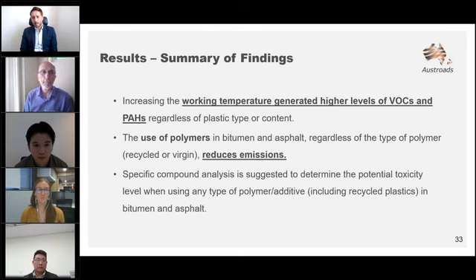No. Well, it's probably not related to slide 33, which is about emissions, but no, in general, we found it difficult to mix more than 2% by weight of the aggregate. Again, it's not 2% by weight of the binder, it's by weight of the total mass of the aggregate. So it is quite a lot of plastics.